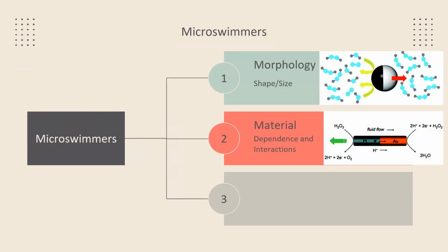So changes to their shape, so having a sort of sphere, Janus-sphere shape with two different asymmetrical sides, with one hemisphere having some sort of coating and the other side of the Janus-sphere being totally different, giving rise to different chemical reactions. For this specific one, platinum, with material dependence, platinum and gold, different bimetallic semiconductor heterojunctions give rise to different electron transfers and give rise to different chemical reactions in our solutions, giving different sorts of motions and propulsion techniques.